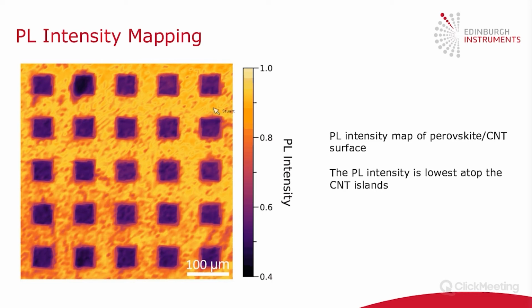So to get photoluminescence, the electrons and holes need to recombine within the perovskite. And you can see this is occurring in regions where we have bright intensity. Where we have the carbon nanotubes, the holes are being extracted by the carbon nanotubes, and therefore they can no longer recombine with the electrons. And you get this drop in the PL intensity on top of these carbon nanotube islands.